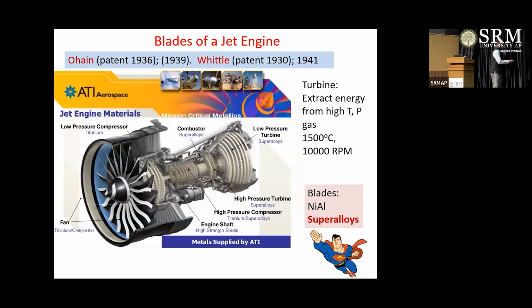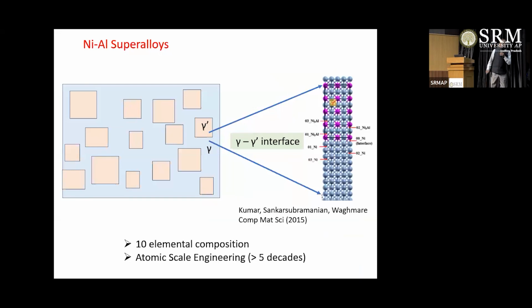So imagine how critical this is. If you didn't have super alloys, you just couldn't take intercontinental flights. So these super alloys also involve very interesting material science. They contain nickel. This blue region means nickel, and gamma prime here is basically nickel 3 aluminum. And this is an example of a material where atomic scale science matters, this interface is shown here at atomic scale. These are nickel atoms and this is nickel aluminum atoms.